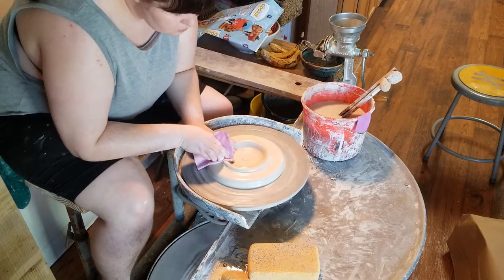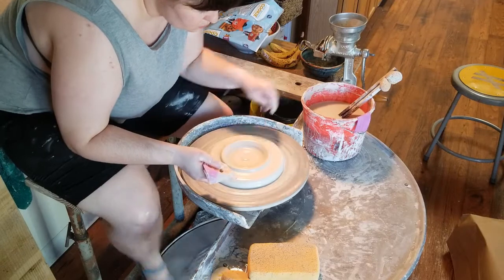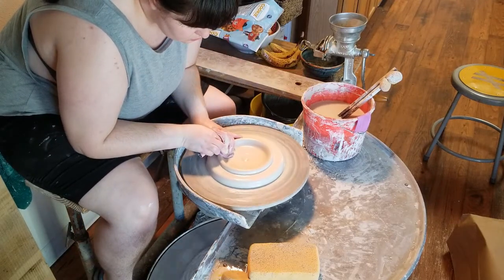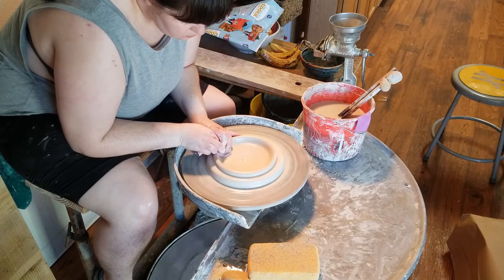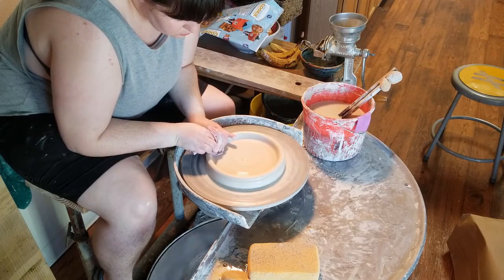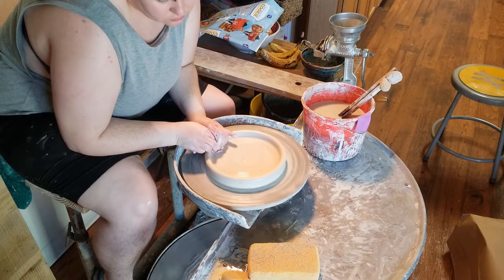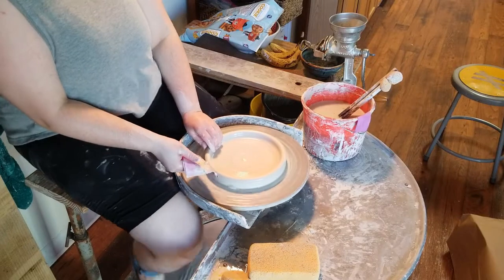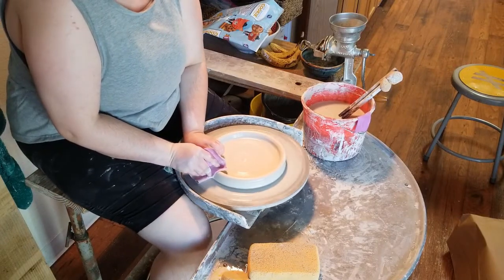I always do this in multiple steps because, as you can see, I'm creating a little lump that I'm moving from the center of the clay to the rim, forming the lip of the plate while doing this. You have to be careful not to pull this little lip off, so while I'm doing this I'm compressing slightly. Sometimes I'll stop and do this in multiple stages, compressing in between to make sure I don't pull it all the way off.